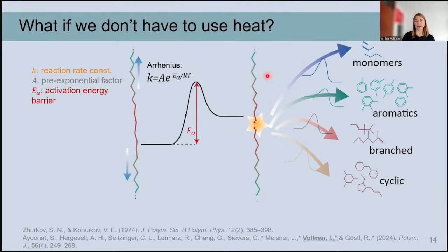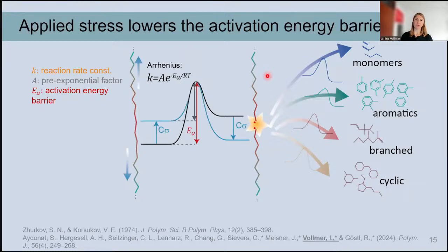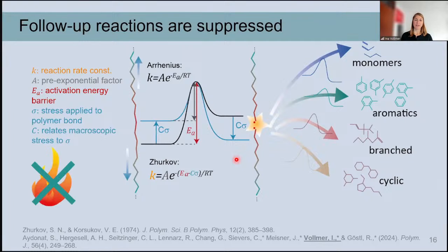So in this way, we actually stretch the polymer bonds, which increases the initial state and energy of the polymer, and thus lowers the activation energy barrier that the polymer has to overcome to be cleaved, as you can see here. And because now we can actually use much lower temperatures, this was observed to happen even at minus 196 degrees Celsius, these follow-up reactions are actually not activated. And at these low temperatures, these activation barriers are much harder to overcome. So this way we can get some control over the products that we form.